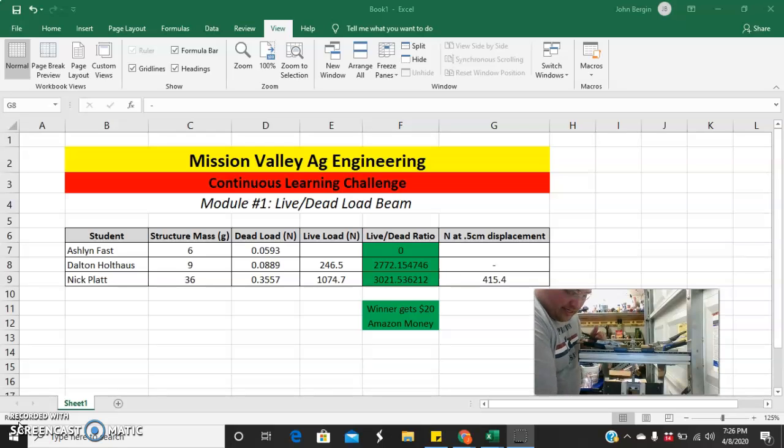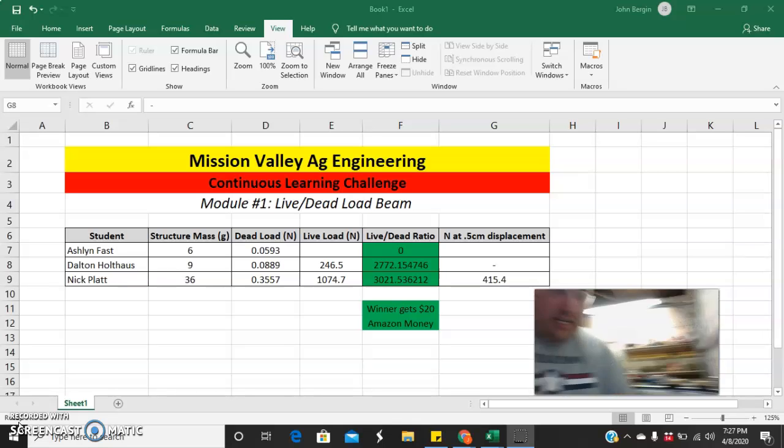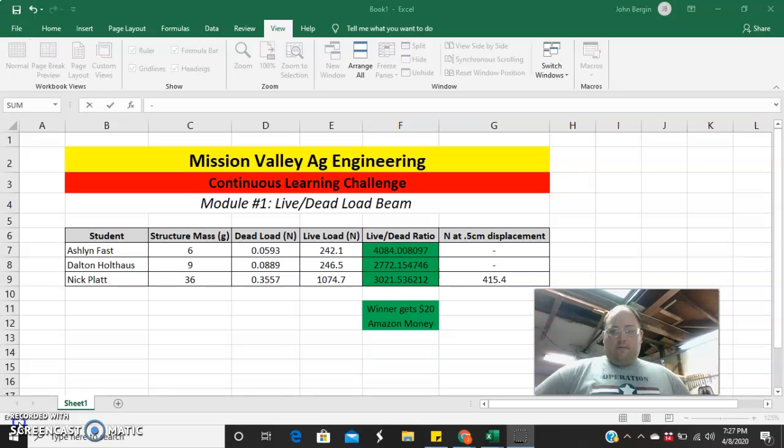Here it's cracking pretty quickly, but it is already at 230 some newtons before it broke. And you can see its break point here, right here. Actually, it's split right down in one of the X's. So let's run, see what the max data is.